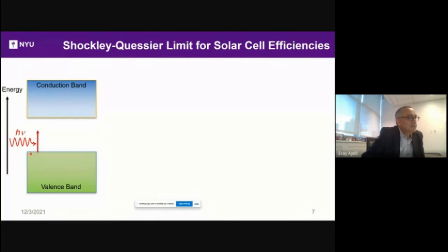So if the photons come in with energies less than the band gap, then they can't excite any electron-hole pairs. They have to come in with energies at least the band gap, so that you create electrons and holes, which are then turned into current and extracted from the solar cell. If they come in with energies higher than the band gap, then these electrons quickly relax to the band edges by colliding with the lattice atoms and making them vibrate more, and therefore creating heat. And that energy is then lost as heat. You don't recover it as potential or as current.